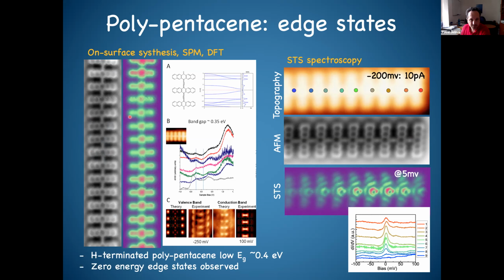Again, we can have a look at the predicted band structure. We can compare the DFT bulk calculations, and again the agreement is pretty good. So DFT is okay, besides the size of the band gap. But more important is that if we look at the end of the polymer, which is terminated perfectly by these hydrogens, now we indeed see a localized state at the Fermi level, and that is only localized at the end. Apart from the states at the valence and conduction bands, now we have evidence of very strongly localized states at the edges.